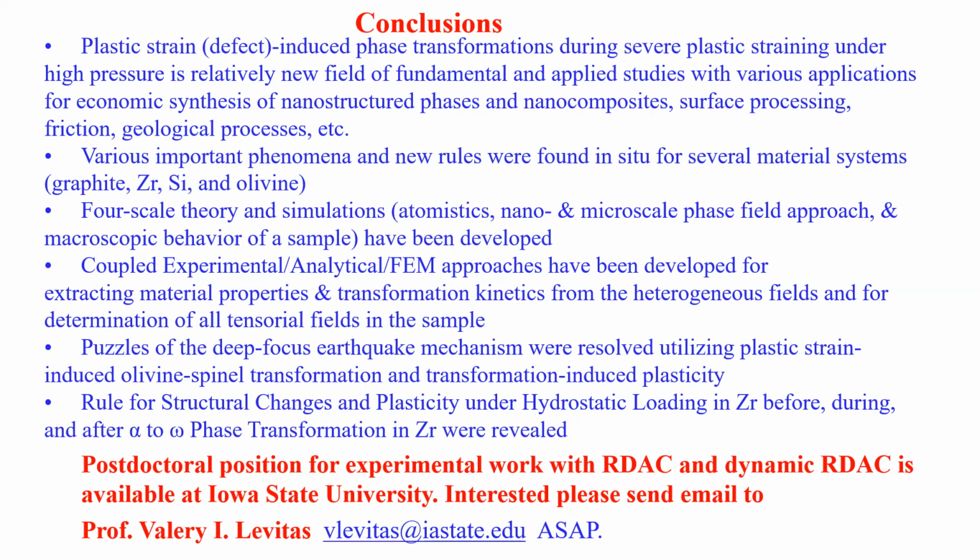Okay. Well, I agree. There is indeterminacy, and I showed this indeterminacy. First, we measure pressure not with ruby, but directly with X-ray. Oh, you mean local? Okay, yes, we resolve that by multi-scale theory. First we determine macroscopic pressures, the macroscopic field, which are average over the size of the X-ray beam, a few micrometers to 10 micrometers. This is the level where we determine macroscopic parameters. And for these parameters, we claim that our phase transformation pressure is, let's say, 1.3 GPa.